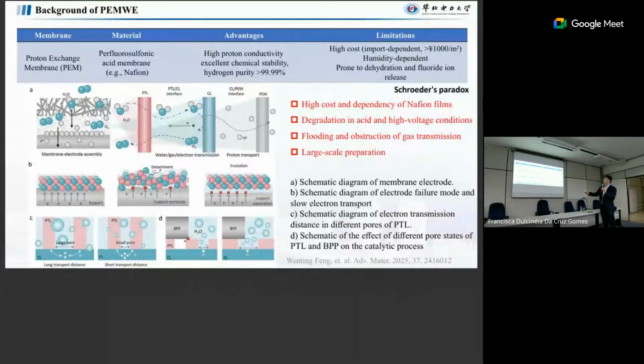And also here, I don't know if you could recognize this. For example, here we put it vertically, at 90 degrees. This is the membrane, this is the catalyst layer, then here we have the PTL layers. Then we can see the protons go from the membrane through the membrane, but here we have the electrons. The electrons go back from the PTL. Also, the water goes in and the oxygen goes out. So the transport of the water and the transport of the oxygen are opposite. The one goes in, the other one goes out.